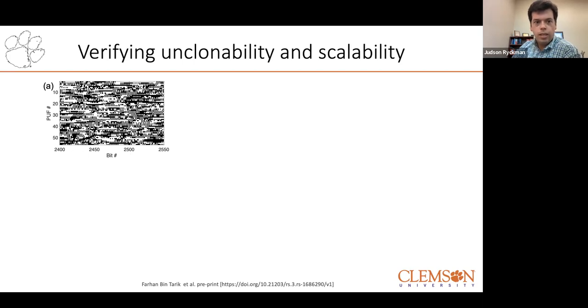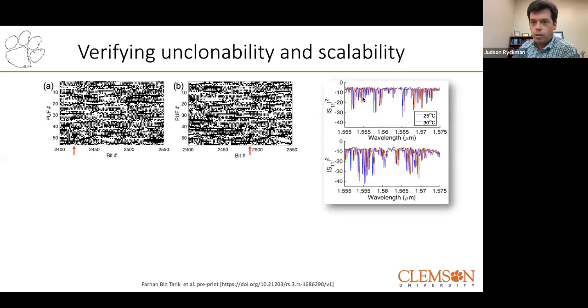And if we look at this key, it does shift with temperature. So if we change the temperature, the spectrum will shift, but that really just shifts where the ones and zeros are along the key. So there's a few bit flips here and there, but it's mostly just a shift of the entire key itself, which is nice.